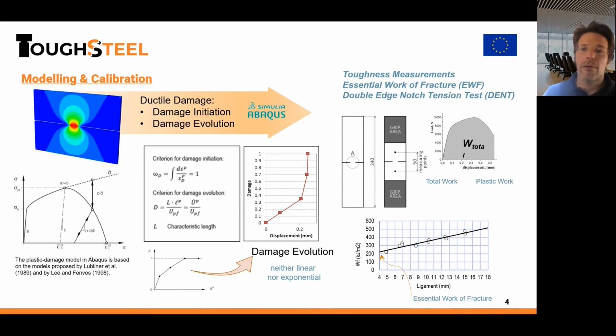To calibrate the model, we obtain the parameters by the toughness measurement, by the essential work of fracture methodology. You can remember the explanation from the previous presentation, and it is through the double edge notch tension, or DEN, specimens. It is a tensile test with two notches, where we have specimens with different ligament lengths between these notches, and with different specimens, we obtain a measurement of the toughness. And a difference from what Ole presented previously, we calibrate the model with the specimen with cracks in the notches.